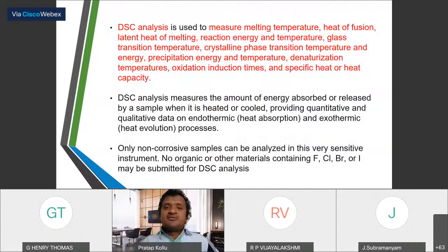Differential scanning calorimetry is used for measuring melting temperature, heat of fusion, latent heat of melting, reaction energy and temperatures, glass transition temperatures, crystalline phase temperatures and energy, precipitation energy and temperature, denaturation temperatures, oxidation induction times, and all these. For DSC, there is a limitation: only non-corrosive samples can be analyzed. So no organic and other materials containing fluorine, chlorine, bromine, iodine may be submitted for DSC analysis.